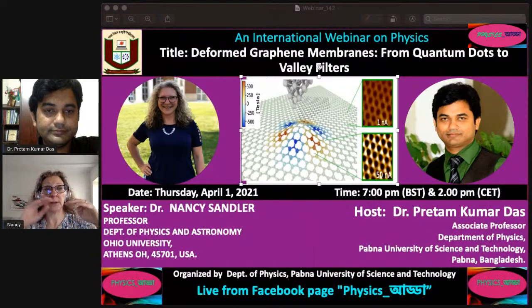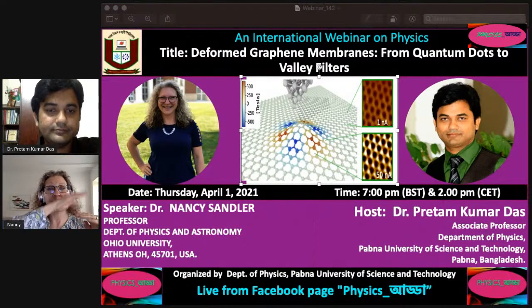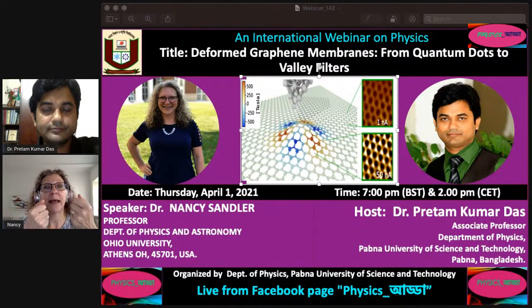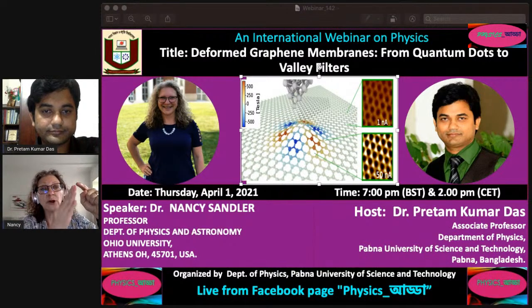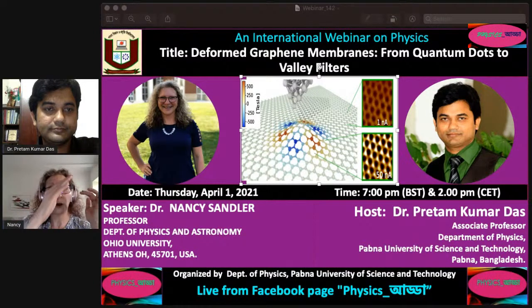One, if you deposit it on a substrate and the substrate has bumps and hills. Graphene is very flexible, but it has some rigidity. So it will follow the substrate as much as it can, not necessarily if the fold is very sharp. Graphene will not adjust so sharply to the edge. It will hang a little bit, but it will follow the rugosities of the substrate.